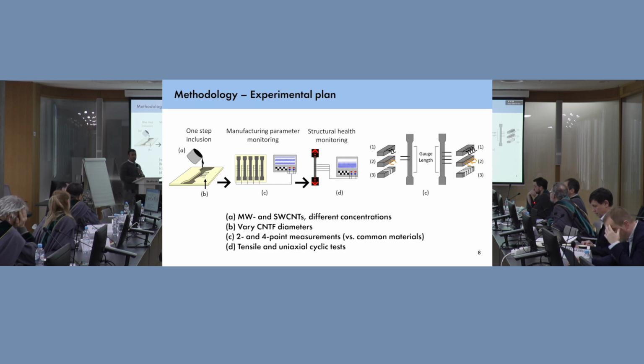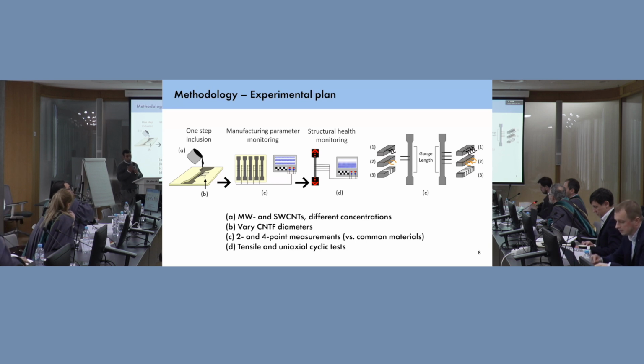Since we're operating at weight percentages which are much higher than just the percolation limit, we still describe it as a percolation network. It's just very well formed. So in this case, there are three things which may happen. One, your amount of ohmic connections can change. Second, your tunneling distance can increase because we're using, in this case, tensile strain. And in our third case, the entire network may deform. So for a very well-formed network here, like the weight percentages that we are using, this would be deformation of the network that we are picking up with our electrodes.